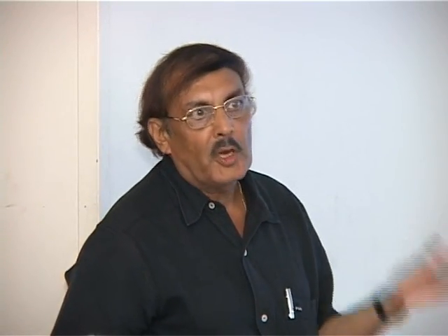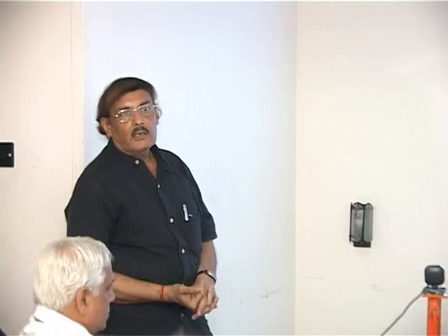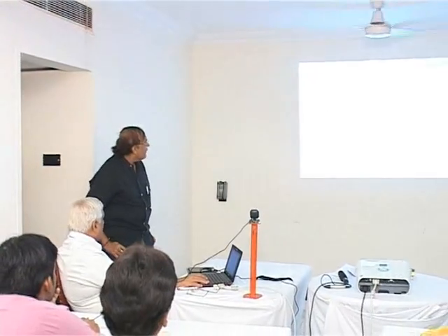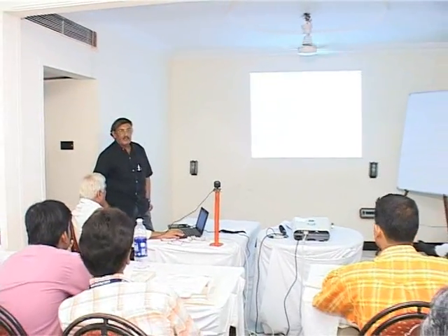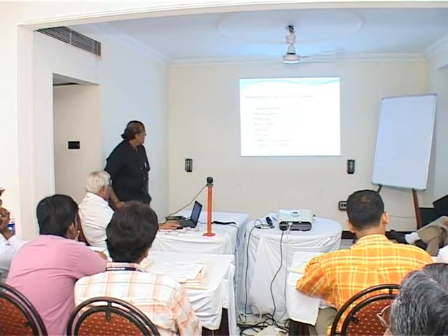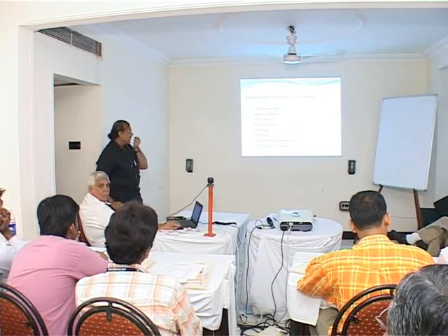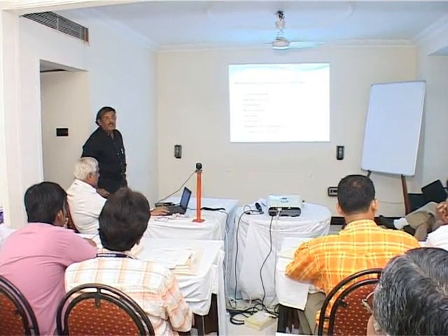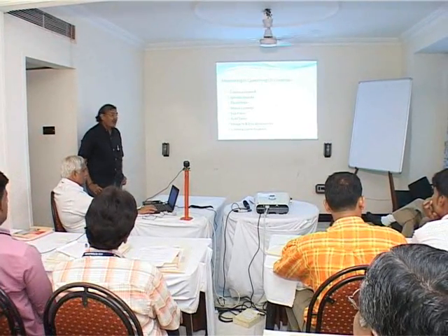The water content: when you are dipping any component, it may contain some moisture, or the oil itself is containing some water. If the water content increases, say from 0.1% to 2.5% or something like that, then the oil is to be discarded. Similarly, the saponification value: if it was previously 77 and has come down to 60, then you need to change the oil. The acid value also: suppose when you took the oil the acid value was 1.5, but it has increased to 2.5 or 2.8, then the oil is to be discarded.